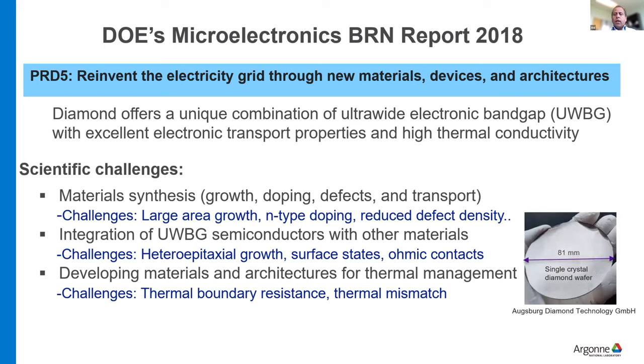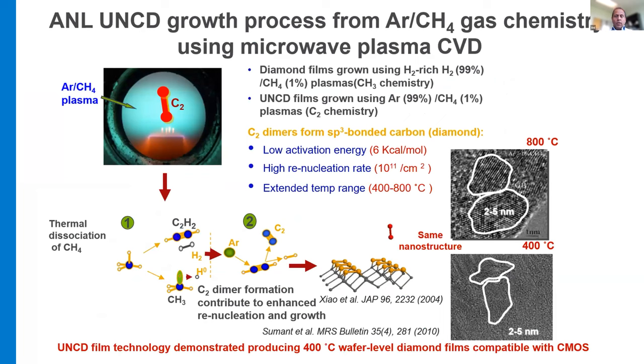Just to mention, you might have seen recently that Diamond Foundry, which is a company in California, worked with a German company and came up with a large area single crystal diamond wafer. This is now also available in 4-inch size. Of course, the defect density is still high, 10 to the 6 to 10 to the 7. But I think this is one of the important developments in the diamond area, where we are now at least talking about single crystal diamond wafers.